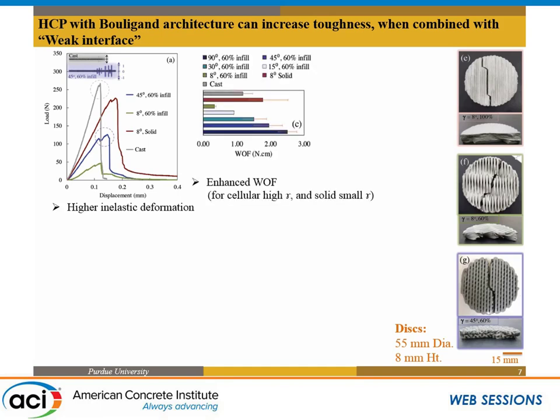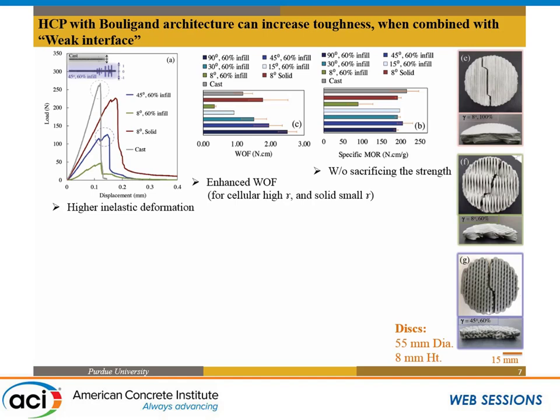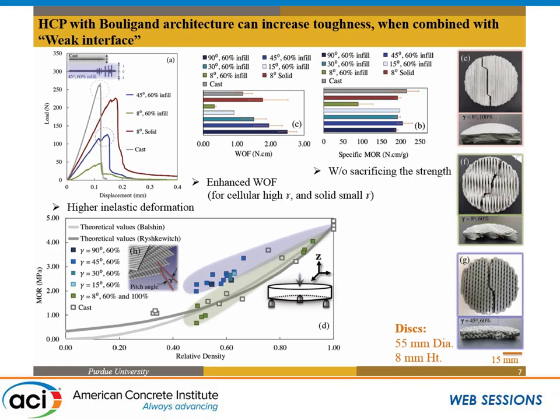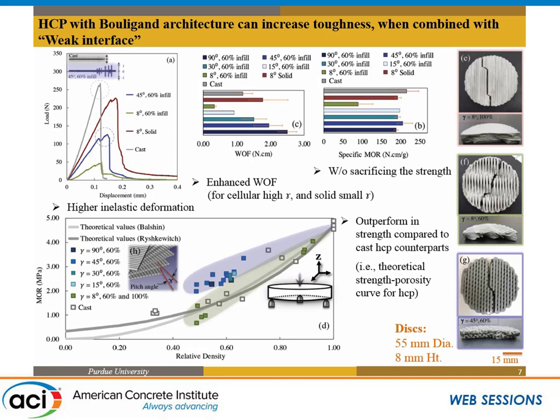If you quantify the total amount of energy absorbed — the work of fracture — you see that as you increase the pitch angle, the work of fracture increases. A solid element with a small pitch angle behaves similarly to another solid element. Importantly, strength is not sacrificed. If we plot all results in a basic porosity-strength relationship, all these Bouligand architectures with different pitch angles and infill percentages stand above the theoretical curve, and some are significantly enhanced compared to their cast counterparts with the same porosity.